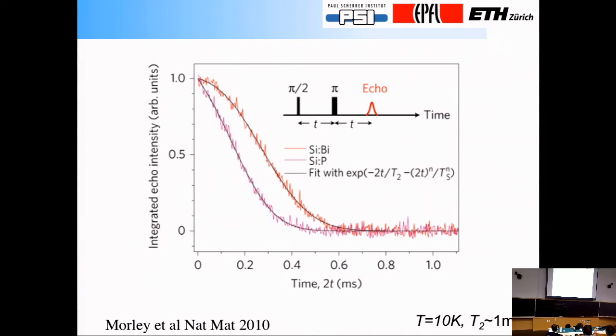And that really means that you can actually hold quantum information in this atom trap for a time that's very substantially longer than the cycle time, for example, for your DRAM in your computer. So in essence, you've already got something here. If you wanted quantum memory at 10 Kelvin, you could address each phosphorus atom individually. You would actually be doing pretty well if you also had processors to match. So this is remarkable. I have this solid, and I have these atoms which are covalently bonded to their neighbors, yet at the end of the day have this hydrogen-like atom with a spin, just the electron spin, which essentially lives forever, compared to any other time scale that you can think of.